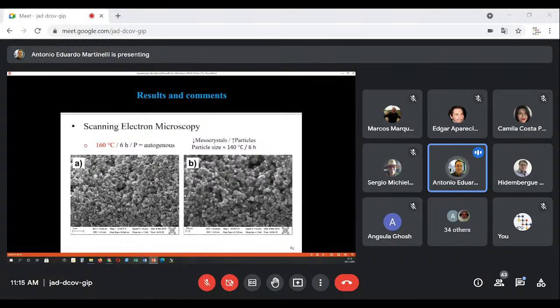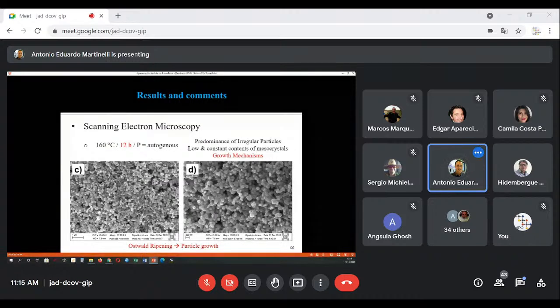And then in this case, we see an increase in the crystallite size. 160 degrees, 6 hours, the system goes on. Particle size is around the same as we saw before at 140 degrees for 6 hours. At 12 hours, now, predominance of irregular particles, low and constant contents of mesocrystals, and the growth mechanisms.